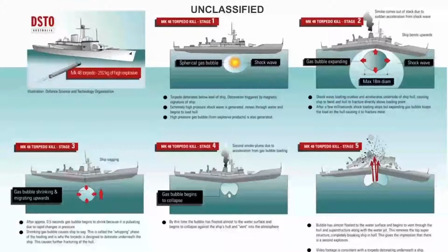This slide was put together to assist the Koreans when we were assisting them in the sinking of the Chonan. So what happens is the torpedo heads towards the ship, it finds its signature, it explodes. That explosion underwater at a fairly deep depth causes a bubble to grow. It grows very rapidly, such that it overshoots its equilibrium, so it gets bigger than what it should be. And then the hydrostatic pressure says, hang on a minute, I've got to squash this back again. So it squashes it back again, and it does it too quick again, so it goes much smaller. So this bubble resonates underwater.